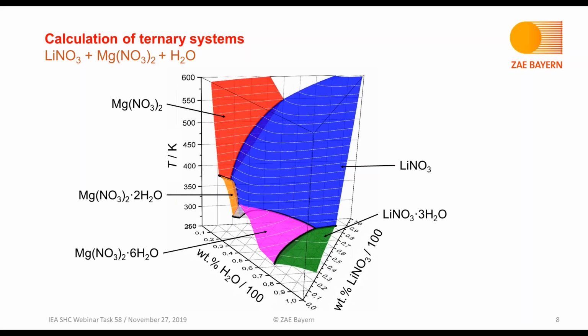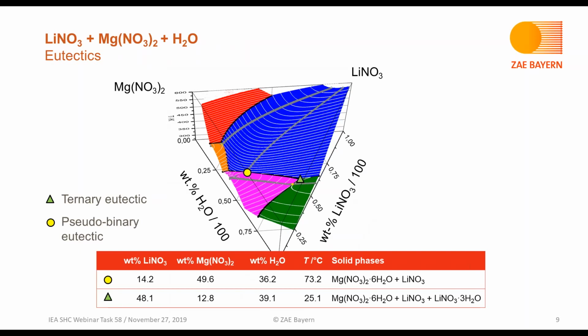So you see the base of the diagram, that's the composition triangle, and in the vertical direction, the temperature is plotted. And here are the different solid phases that occur in the system, the 2 anhydrates and then several salt hydrates. What is interesting in terms of PCM development is the location of the ternary eutectics. In this system, 2 types of eutectics occur, ternary eutectics and so-called pseudo-binary eutectics. The calculation result is the composition and the temperature of these eutectics, as indicated in the table at the bottom. For the pseudo-binary eutectics, we have 2 solid phases in equilibrium with solution, and in the ternary eutectic, there are 3 solid phases in equilibrium with salt solution.